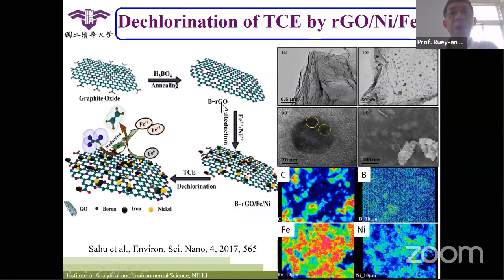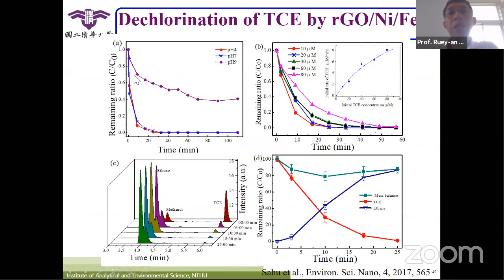We just use boron-doped reduced graphene oxide and then add iron and nickel, and they will reduce to zero-valent iron and nickel. So this is the case here. We use this to decompose trichloroethylene, a chlorinated compound. In just around 20 minutes, all the chlorinated compounds can be decomposed, and they convert into ethane. So that will be good.